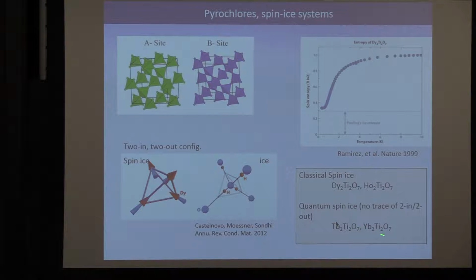The quantum spin ice has no such order, and as I mentioned, it remains disordered down to very low temperatures. So there are two of them that we studied. I will just tell you about terbium. Ytterbium behaves more or less the same way. Actually, ytterbium is an even better example than terbium, but that came a lot later.